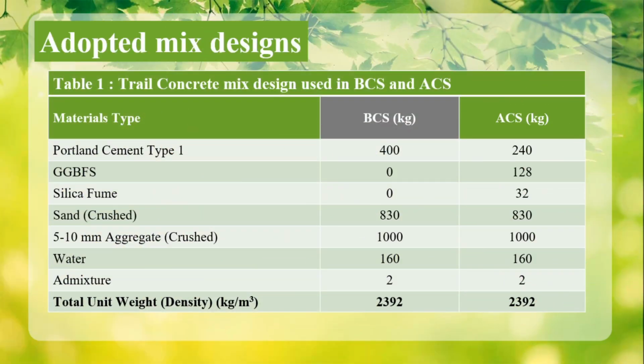First of all, a base mix design, or BCS, was defined based on common local practice, which includes 400 kilograms of Portland cement per cubic meter of concrete. Then, according to the competition guidelines, an alternative mix design, or ACS, was developed, which replaced 40% of the cement with SCMs while keeping the water to binder ratio constant, including 32% slag and 8% silica fume. These two mix designs form the basis for comparing durability and environmental impacts.